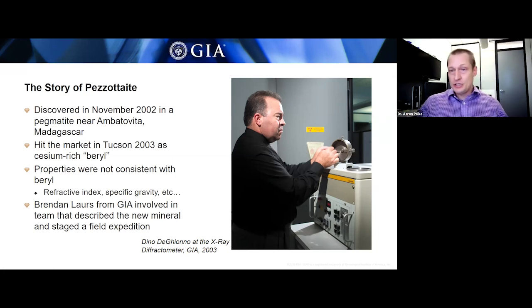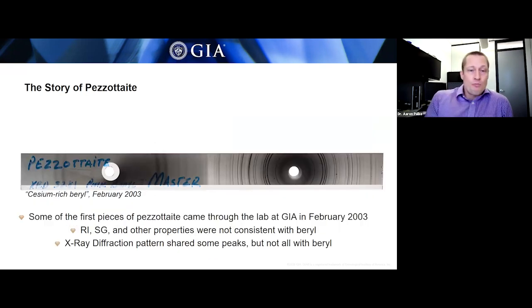And so this is what Dino did with this new mineral that came in. And I actually went through the archives we have here and dug up the original X-ray pattern that Dino had collected on this Pezzottaite in February 2003. So this is probably one of the first X-ray diffraction patterns, if not the first, to ever be collected on Pezzottaite. This looks a little bit different than what you saw with Evan's examples of the X-ray diffraction patterns, but what you're basically seeing is those diffraction lines in these circles around the center of this film. And each different mineral would have its own unique fingerprint in this X-ray diffraction pattern that you could use to identify the mineral.